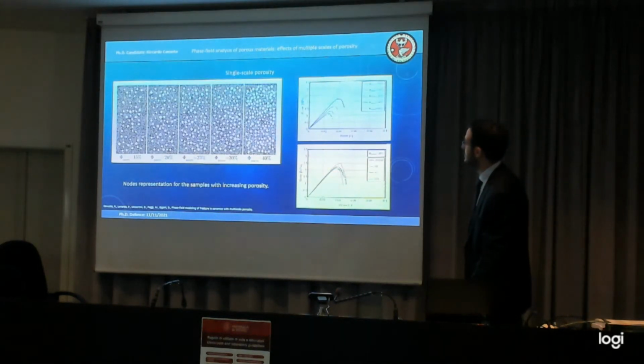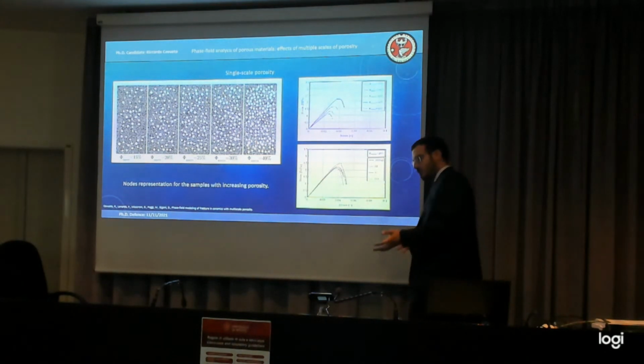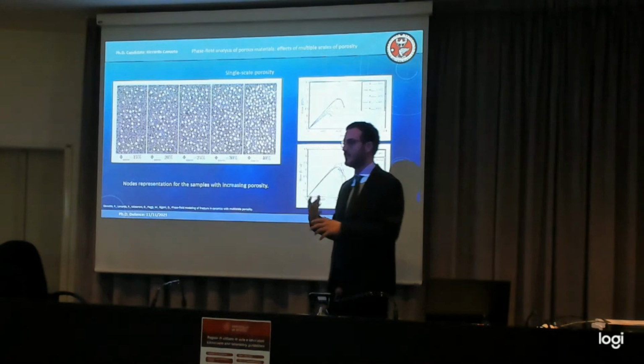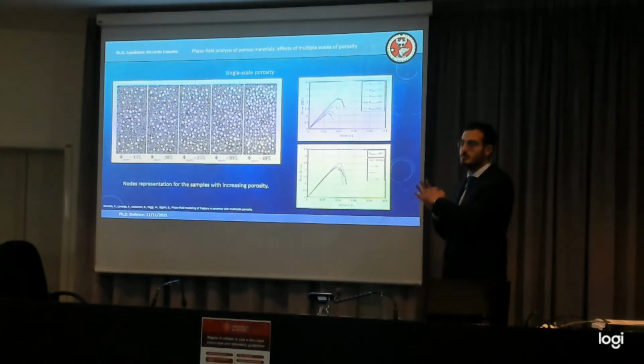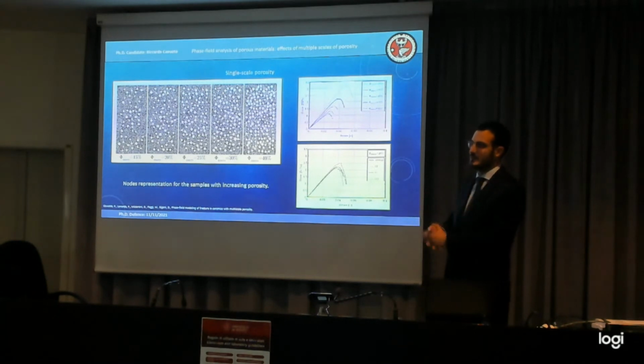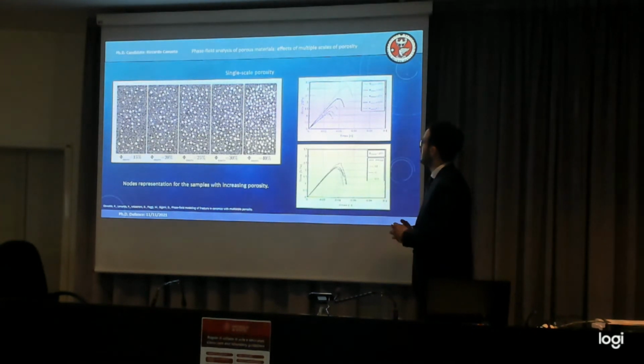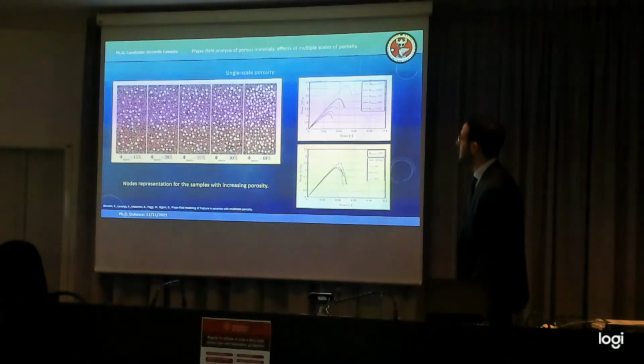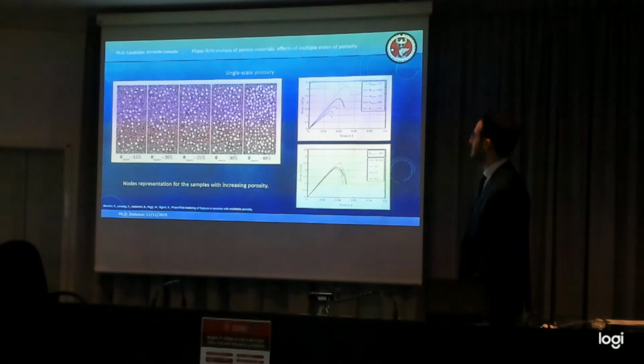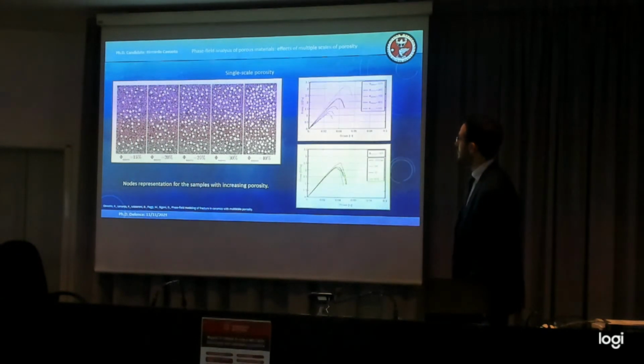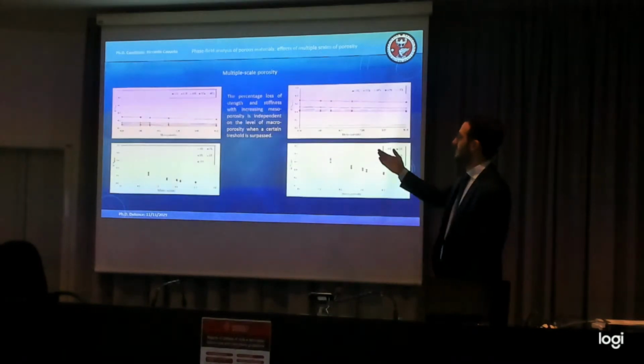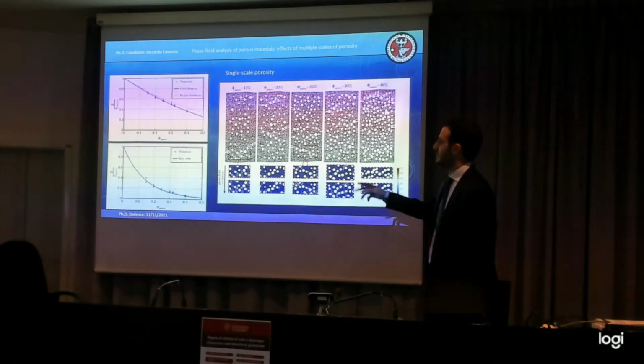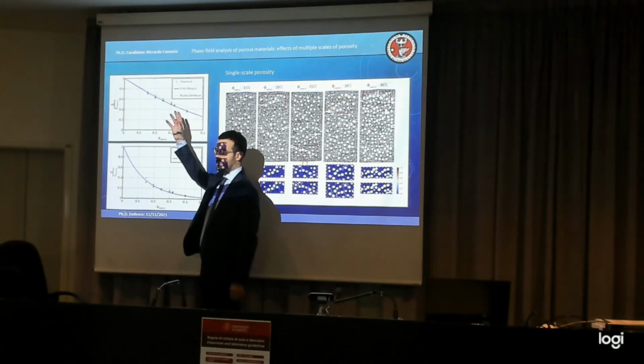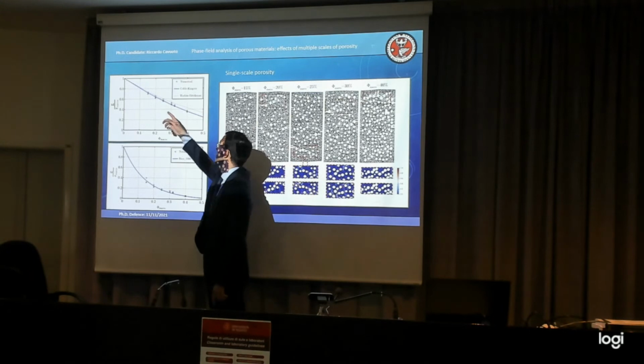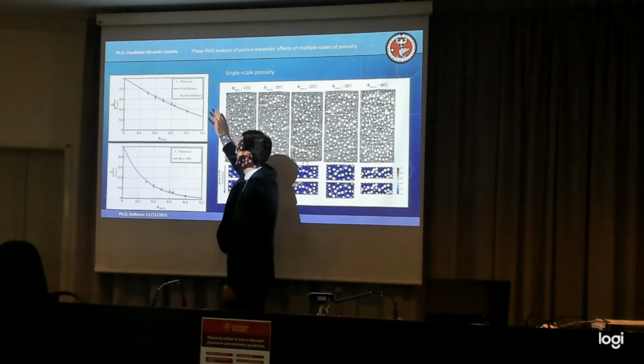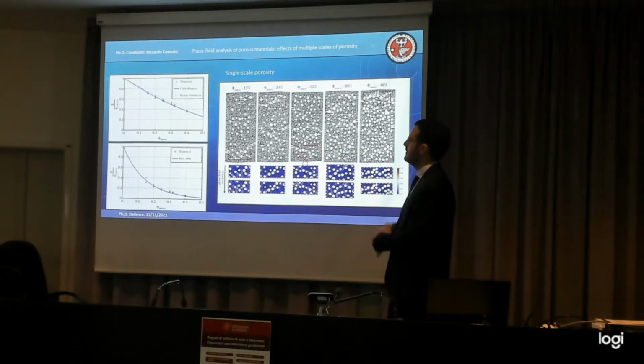So this is calibration, and we wanted to analyze the effects of single porosity or multiple porosity on the crack pattern, and to see if by using the phase field, it's actually possible to reproduce what is happening in the ceramic we're starting to create. And this is the analysis in the case of a single porosity. We have tried out many different levels of single porosity. The overall properties of the models are listed here, and obviously the overall properties are easily reproducible. There are a lot of analytical formulations to predict the overall behavior. There is the Kuster-Toksöz approach, the Hashin-Shtrikman bounds. They're all very good to approximate the overall behavior.